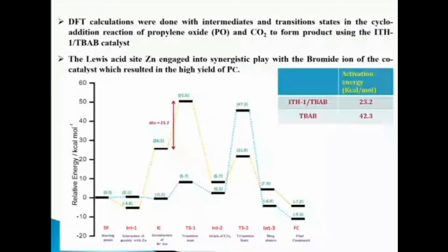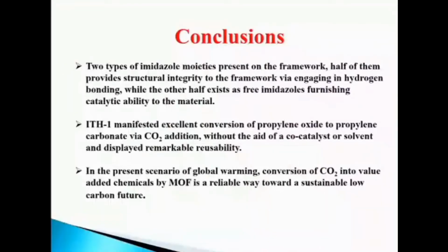From the results and catalytic studies, we could conclude that there are two types of imidazole moieties present on the framework. Half of them provide structural integrity to the framework via engaging in hydrogen bonding, while the other half exist as free imidazole furnishing catalytic ability. And our ITH1 manifested excellent conversion of propylene oxide to propylene carbonate via carbon dioxide addition without the aid of co-catalyst or solvent, and displayed remarkable reusability. In the present scenario of global warming, conversion of carbon dioxide into value-added chemicals by MOFs is a reliable way toward a sustainable low-carbon system. These are some references used. Thank you.